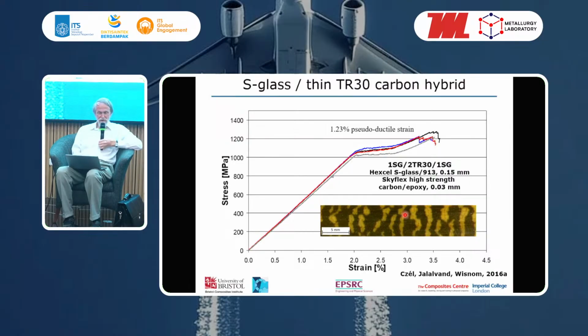I don't think you can see it on here, you might just be able to see it. In the middle of those yellow patches is a black line, and that is actually where the carbon fibre has broken. So it's broken locally, with a little bit of local delamination, which creates an interface, and because of the translucency of the glass, you can see it now becomes yellow. Then over here we have another fragmentation, and along the length we have these multiple carbon fragmentations, and between them it's still intact. And that's what gives us this plateau on the stress strain curve.